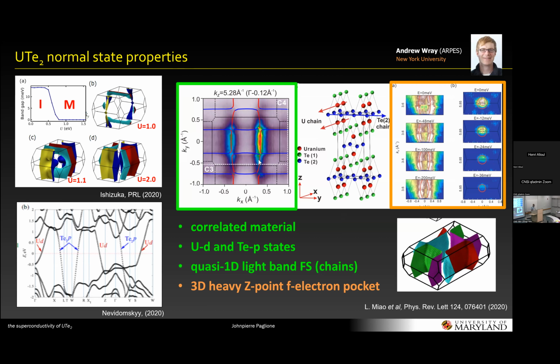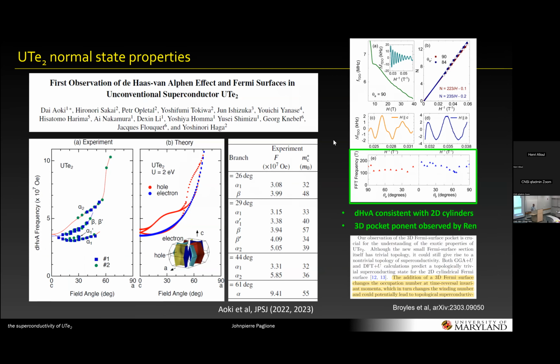And then some ARPES and other studies have shown, pretty conclusively now, that the Fermi surface is composed of these quasi-1D sheets that arise from these uranium and tellurium chain structures, shown in the band structure here. These are composed of these d and p states that are not f weighted. These sheets are sort of hybridized to give you these cylindrical-like shapes that were observed. There's some aspect of a potential f-weighted circular pocket that was observed in ARPES. This has also been more recently confirmed through quantum oscillation studies, which is quite nice. And these are these lower residual resistivity samples that have been made.